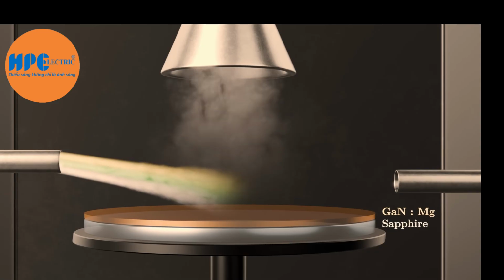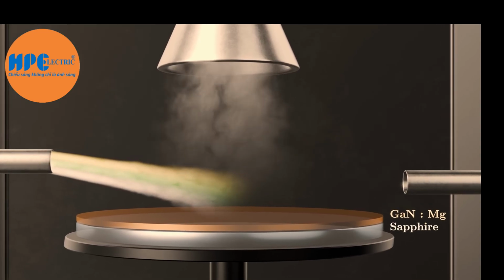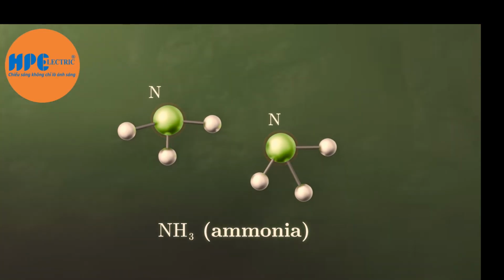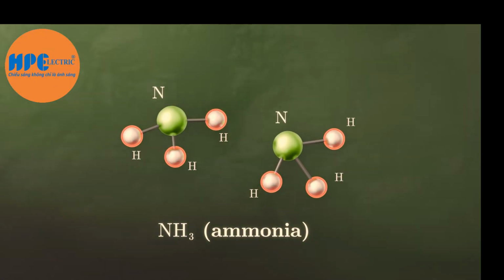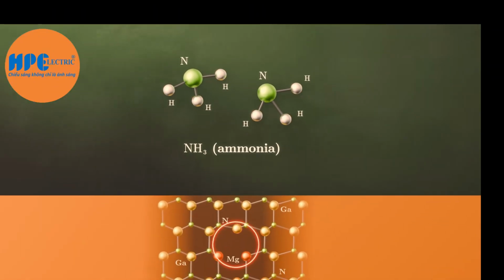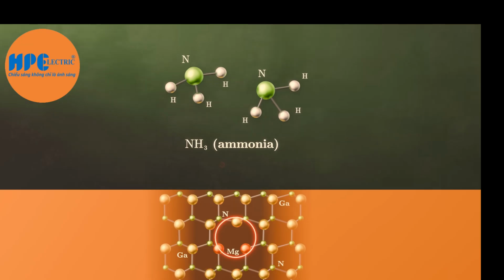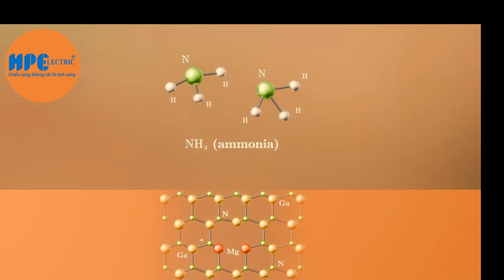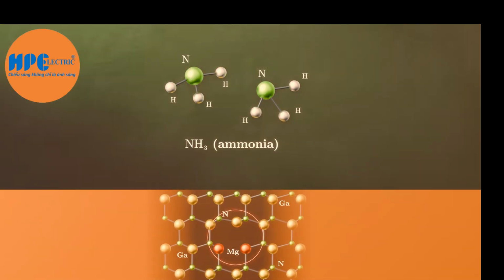His work also revealed why the p-type had been so difficult. To make gallium nitride with MOCVD, you supply the nitrogen from ammonia. But ammonia also contains hydrogen. Where there should have been holes in the magnesium-doped gallium nitride, these hydrogen atoms were sneaking in and bonding with the magnesium, plugging all the holes. Adding energy to the system released the hydrogen from the material, freeing up the holes again.